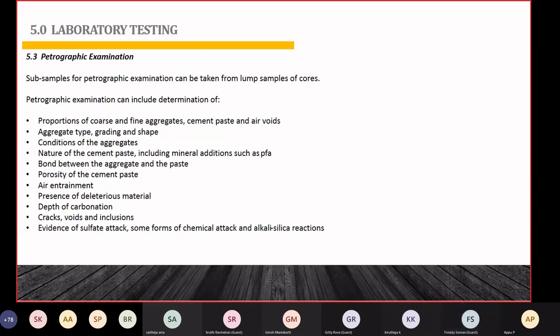But normally, as I mentioned before, for corrosion we do both tests together. Same way, in order to find out the cement content correctly, particularly in complaint cases and arbitration cases, mostly we will go for both tests. One is the chemical method, and the second is the petrographic analysis, to find out the exact cement content in the concrete. You have to keep that in mind.